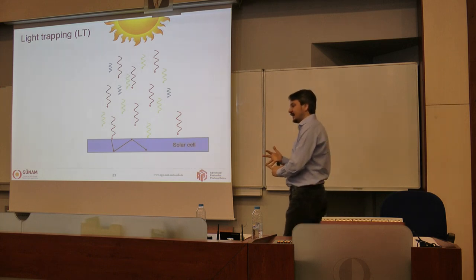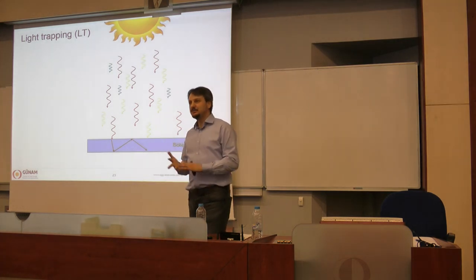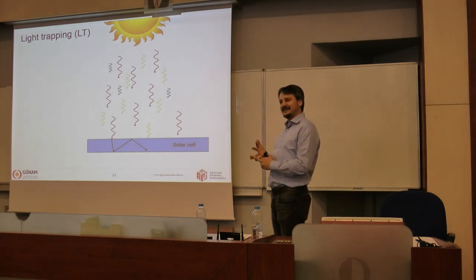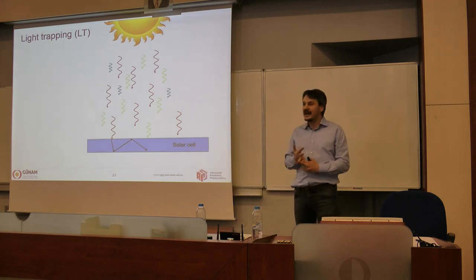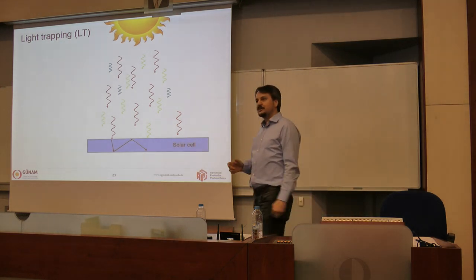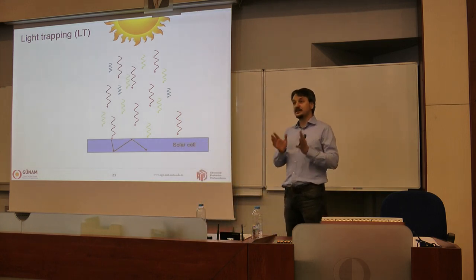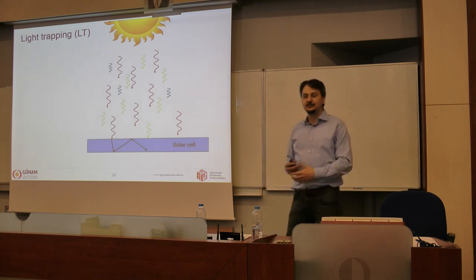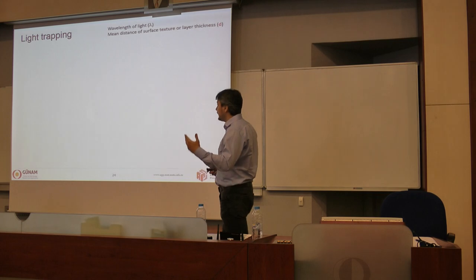So if you hear something like, hey, there is one guy who made a transparent solar cell, right? Which I'm sure you have seen from the news at some point, then I say, how is it possible? If it is transparent, that means it's transparent to the eye. That means it doesn't absorb the light in the visible colors, where most of the photons are coming from. So by saying I'm gonna make a transparent solar cell, you have to sacrifice 70% of the solar spectrum away, and the other 30% you can utilize and get like 5-6% efficiencies, which are the theoretical maximum. And the first thing we need is to absorb the light, and how are we gonna do it?